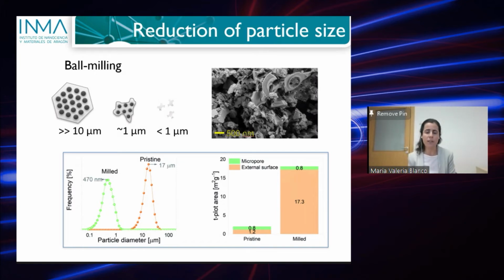particles. And as you can see, the shape of these particles is not spherical, but rather irregular. And after the milling, what you can see on the graph, that is the t-plot area, the external surface area of the algae increased quite a lot after the milling, but the micropore area remained the same, which is what we expect. Right? With the milling, we just increase the surface area that is exposed.